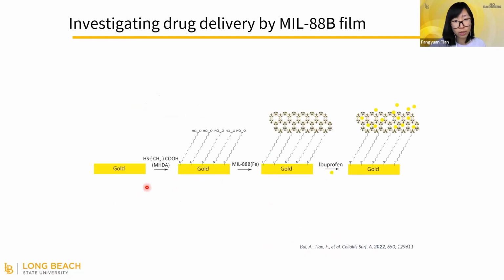We started with a gold surface because it's chemically pretty inert and simple. So we can use a thiol-containing self-assembled monolayer to modify the surface. And because of the carboxylate groups on top of the monolayer, we can directly connect it to our MIL-88B crystals. After that, we'll do the drug loading, see how much drug can be loaded there, and monitor the drug release process.